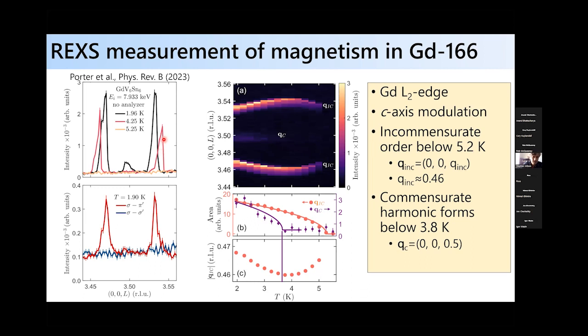You can see these peaks slide in and evolve a bit as you continue cooling. At the lowest temperature, there's an additional peak that appears at the half integer position. If you look at a map of intensity as a function of temperature, you can see the Q vector of these incommensurate peaks evolving, initially expanding outward and then coming back in as you cool toward the ground state. Right at this bend, or inflection, you can see the onset of a weak commensurate harmonic appearing at the 0.5 position.